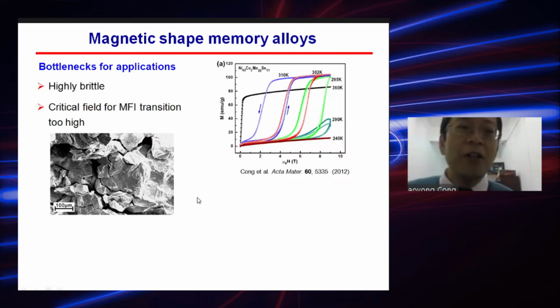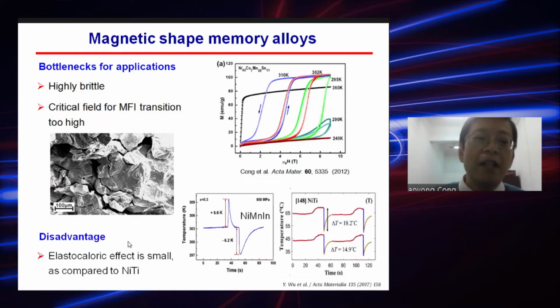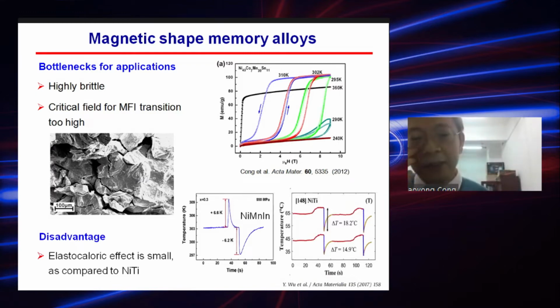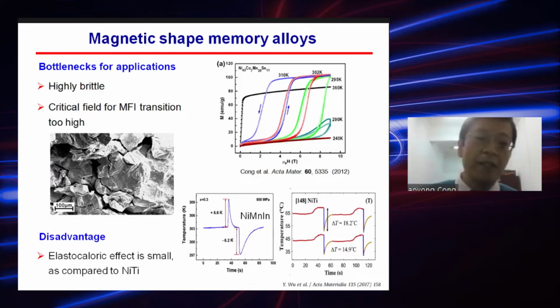However, these kinds of alloys are very brittle, and the critical field for magnetic field-induced transition is too high, which are two bottlenecks for applications. Another disadvantage of this kind of alloy is that its elastocaloric effect is small, especially when we compare it with nickel titanium.